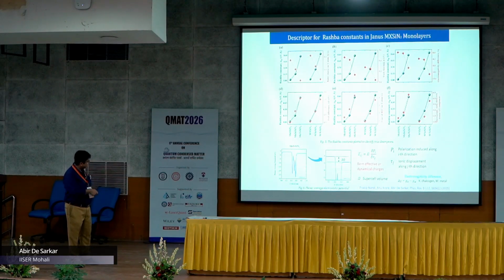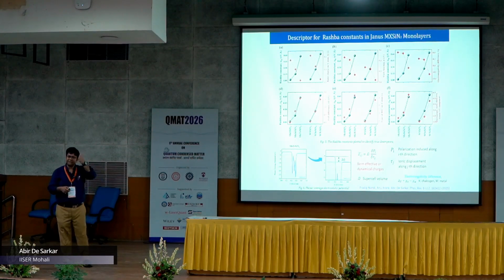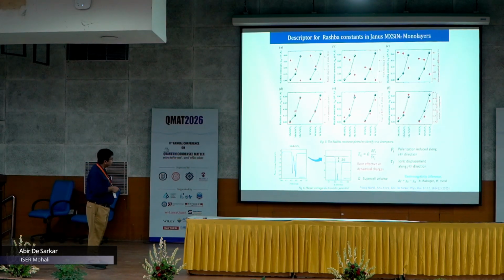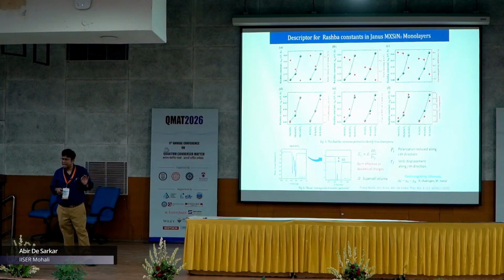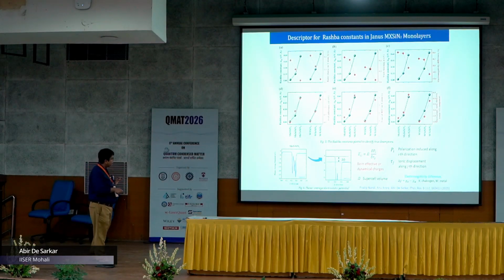Now, the negative gradient of this electrostatic potential builds up an electric field along the z direction. So, the higher the out of plane electric field, the higher the Rashba constant. That is what we find here, and the Rashba constant is also found to scale with the trace of the Born effective charges on the chalcogen atoms. The Born effective charges are not the static charges, these are the dynamical charges.